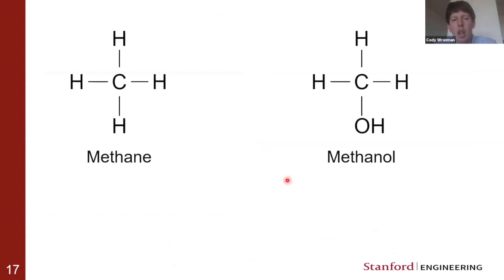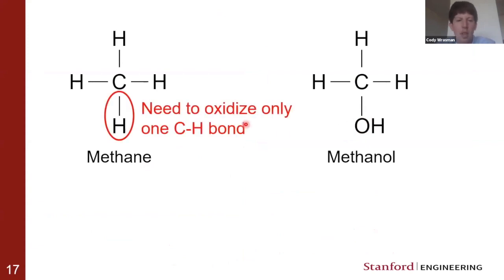So it'd be great if we could start trying to recover that methane into a more valuable product that we could start using. I'm showing here the molecular structures of methane on the left and methanol on the right. You see that they're almost identical. You just have this extra oxygen inserted into methanol. So kind of naively, that seems like it should be a very easy transformation. We just need to oxidize one of these carbon-hydrogen bonds to form methanol.